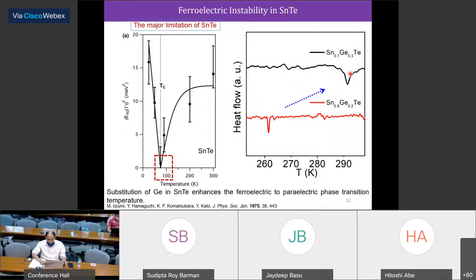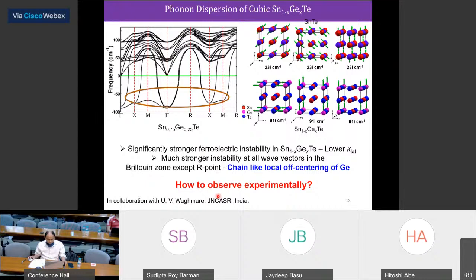Then we collaborated with Umesh Waghmare from JNCASR, who showed that the ferroelectric instability increases hugely in this germanium doped tin telluride, and the unstable phonon mode we have observed at all the points except the R point. And if we do the Fourier transform, we found that there is a chain type local germanium distortion. So I'll summarize in layman's words: basically we have a global rock salt structure of tin telluride, and when we dope germanium, the germanium locally distorts in a chain fashion, but the global structure is cubic.